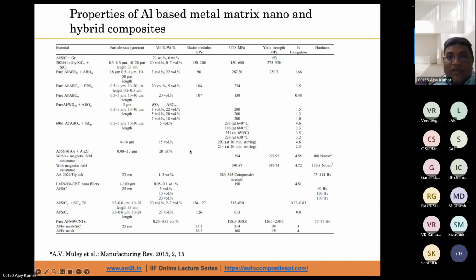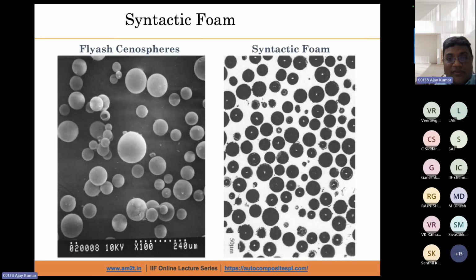And you can see the UTS, the ultimate tensile values, and the yield strength values also increasing, and the percentage elongation. So most of the things we will face problem with the ductility. Ductility of the cast metal matrix will decrease because sometimes the dispersion and the interface between the matrix will not be bonded properly. So that is why we face a reduced ductility problem in the cast MMC. We can get the good strength.